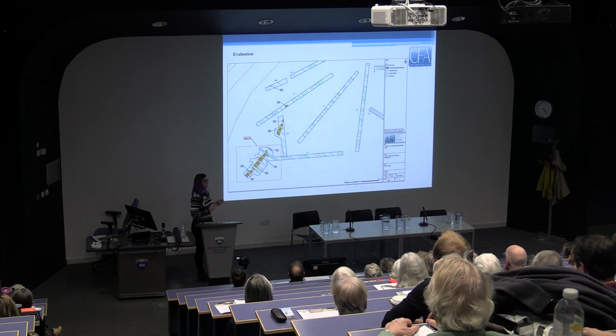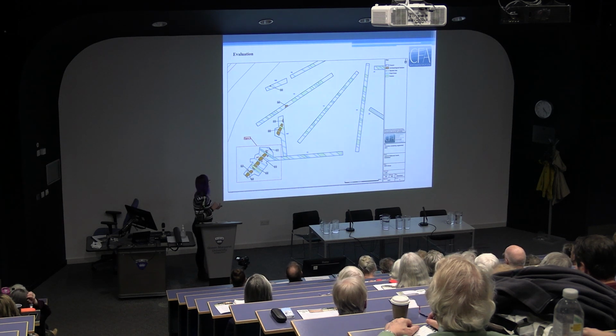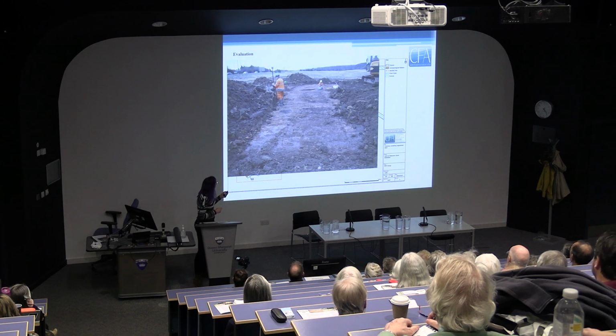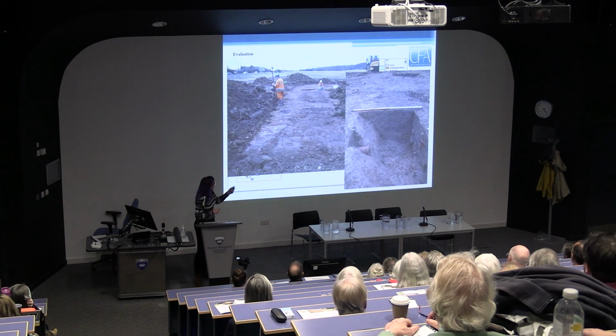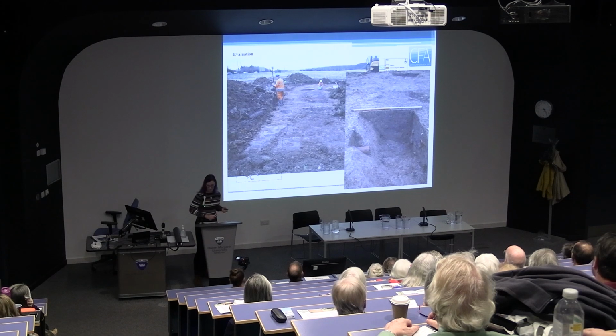At the time, again, because last day, we only had time to dig 2 slots here and here into ditch 2, where we recovered 3 fills with slag and fired clay coming out of the upper fill. So these are 3 of the ditch segments there, Harry and I hard at work. And then this is a slot, you can see the darker upper fill that contained the slag.